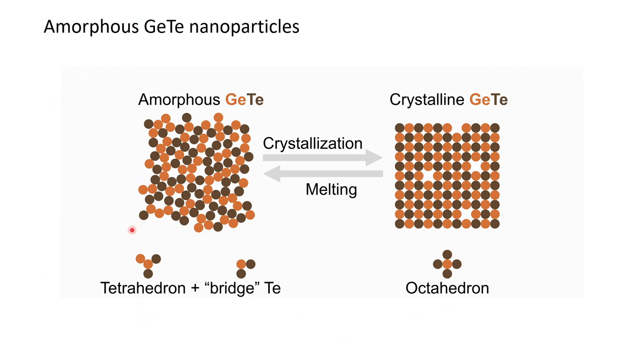Now what about amorphous? You remember that we have 2 different units, germanium-germanium and germanium-tellurium. This would correspond to so-called tetrahedron and bridging tellurium units. And they should be in about a 1-to-1 ratio in the structure. So we did that. We just managed to tile 2 dimensions using only these 2 structural units. And it works. So that means that the structure looks very amorphous, right? But it's possible to classify it quite simply.